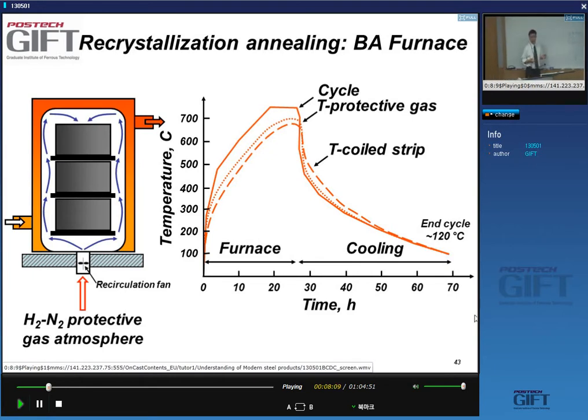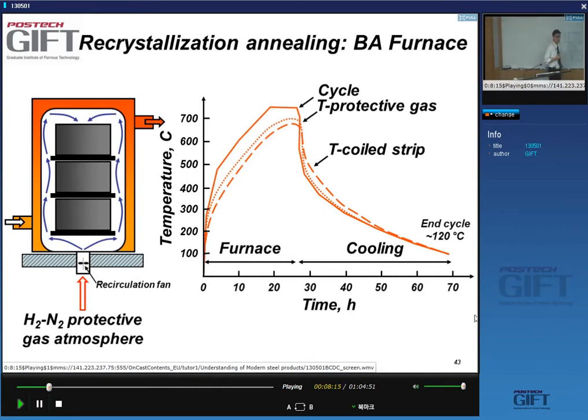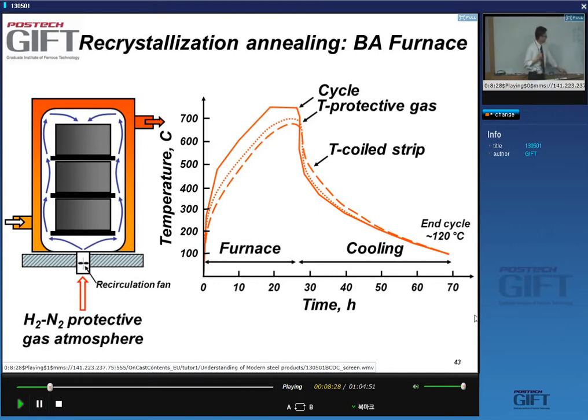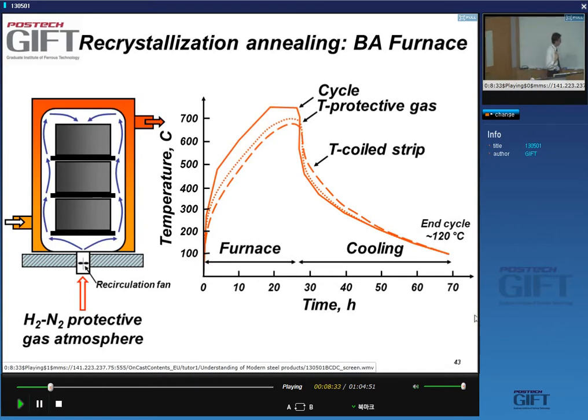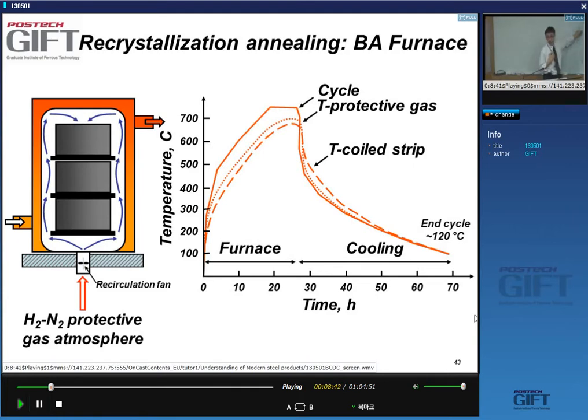It's going to be a big variation. You have to make sure that your product is not sensitive to these big differences in thermal cycles. In particular, you don't want to have grain growth in the outer region while the inner region had very little grain growth because it wasn't at high temperature for the same amount of time.